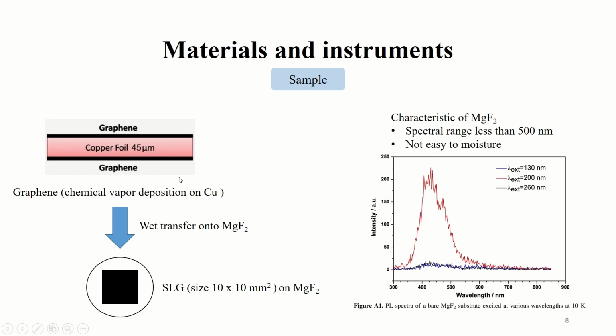Let's introduce the sample. The graphene sample was purchased from SES Material. The graphene is grown by chemical vapor deposition on copper, and after wet transfer onto MgF2, it gives a single-layer graphene on MgF2. The reason this paper chose MgF2 for the experiment is that previous studies didn't investigate single-layer graphene on magnesium fluoride. The other reason is that it is stable and not prone to moisture.